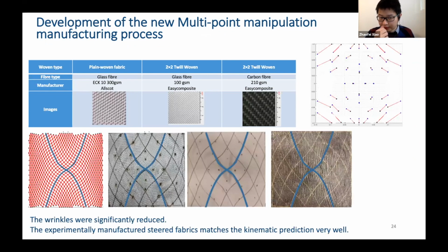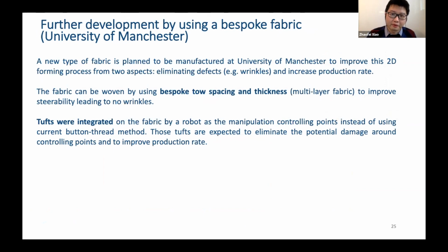So if we compare the results, we can say the wrinkles were significantly reduced, and the experimentally manufactured fabrics match the predicted steered pattern very well. So that's a very good achievement. And in order to further develop this manufacturing process, we teamed up with the University of Manchester. We want to manufacture a new, bespoke type of fabric with bespoke tow spacing and thickness to improve the steerability, leading to no wrinkles in the fabric.